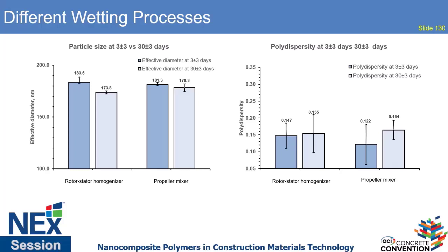So we decided to try something with lower energy, like a propeller blade mixer, just to see if the wetting out method, as long as it is followed with sonication, would be sufficient. From the studies, we can see there was no significant difference whether you use a rotor stator homogenizer or a propeller mixer, as long as sonication follows right after. This was supported by both the polydispersity and the particle size. You can see that we measured the particle size and polydispersity at 3 days and 30 days, and there was not a significant increase. So even though the particle size was not necessarily less than 100 nanometers, it is still a system that was dispersed, and the overall stability of the material was there.